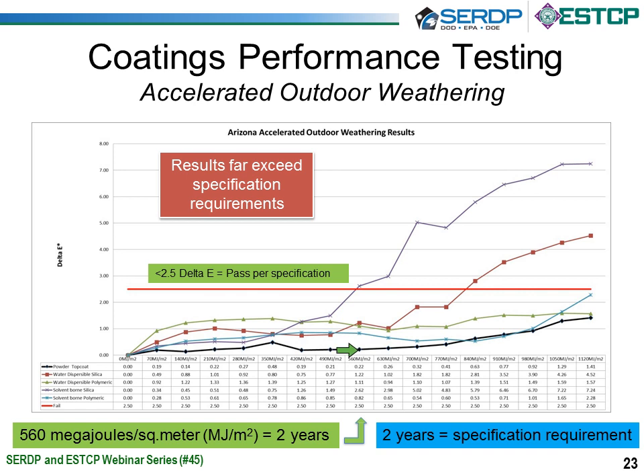So we have a delta E of 0.2 after the specification requirement, the pass-fail criteria being 2.5. So we doubled the requirement for the specification, and we were still well below pass-fail. So we're far exceeding the specification requirements for exterior durability. This is a big win. You can see the traditional coatings were up here. I'll speak a little bit more of the benefits of that, but if you can imagine, if the paint doesn't fade and it retains its durability, then we're repainting less.